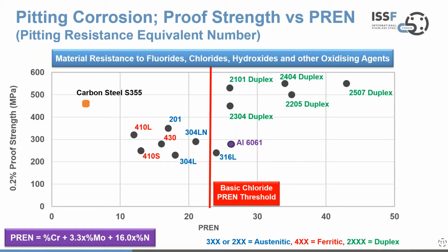So now let's try and put some of that in context using one example. And this example is pitting corrosion, which occurs when you have fluorides, chlorides, hydroxides, and other strong oxidizing agents present. And this chart shows the strength represented by the proof strength on the y-axis on the left-hand side, and what's known as the pitting resistance equivalent number, which is derived from the chemical analysis. It's described in a little box in the bottom left-hand corner.